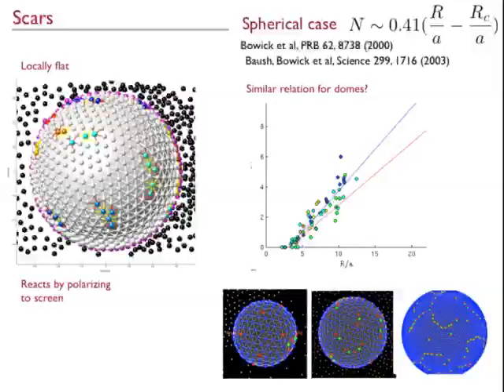So these guys figured out you can do something really clever. What you can do is you can take pluses and minuses. Remember, these are like charges, right? If you want to screen a charge, what you can do is you can arrange positive and negative charges around it to screen it. Positive and negative charges together are dislocations, so you can screen a disclination by having strings of dislocations emanating from them. And that's what they called scars. And so when you get big, what it depends upon is the lattice spacing compared to the radius of the sphere.